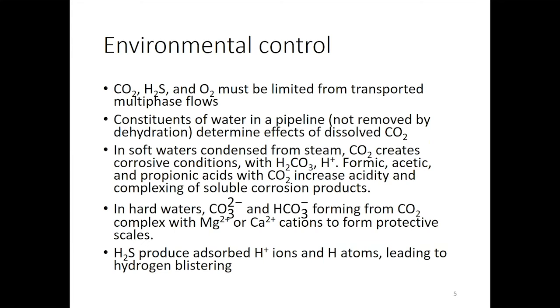So as I said earlier, for environmental control, we consider the concentrations of carbon dioxide, H2S, or oxygen, which must, of course, be limited. The constituents of water in a pipeline are not removed, of course, by dehydration. We also determine the extent of the expected damage of CO2 in soft waters condensed from steam. CO2 creates corrosive conditions. We know carbonic acid and reduced pH drive and accelerate the cathodic reactions.